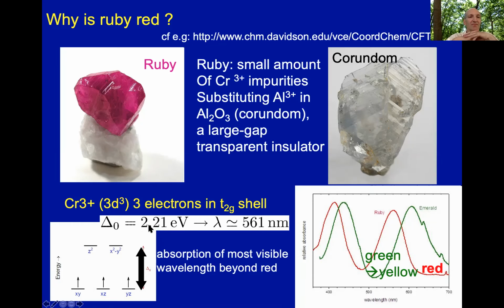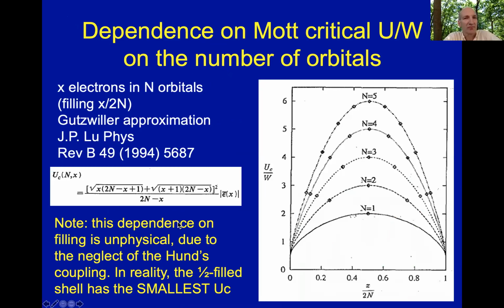So this value, or if you want in terms of wavelength, being about 560 nanometers, means that everything which is between 1.8 eV and 2.2 eV, which is basically red light, will pass through the crystal, but everything which is higher than that will be absorbed, and as a result, the material is red. So this is why ruby is red, and this is why crystal field is important.